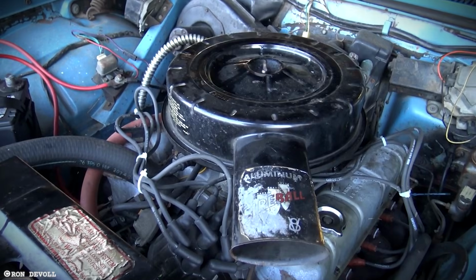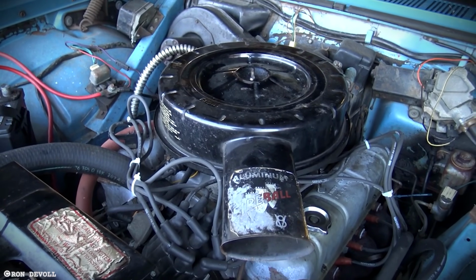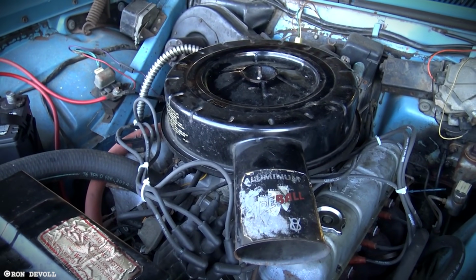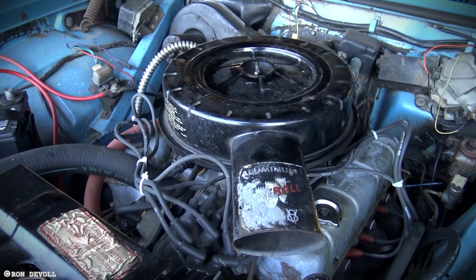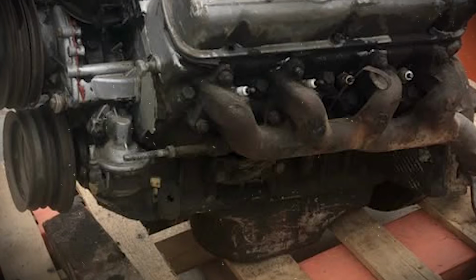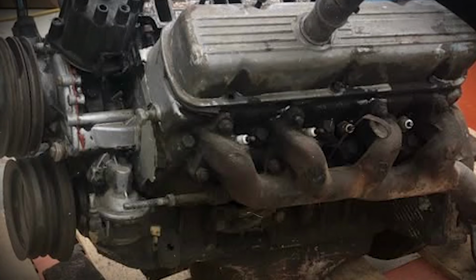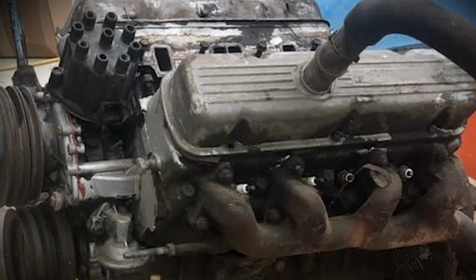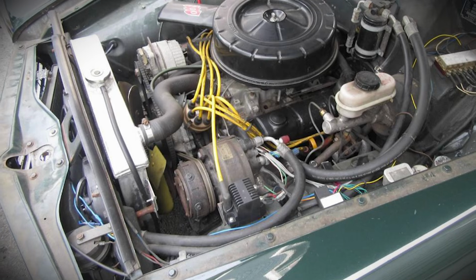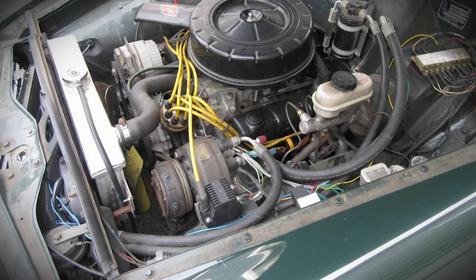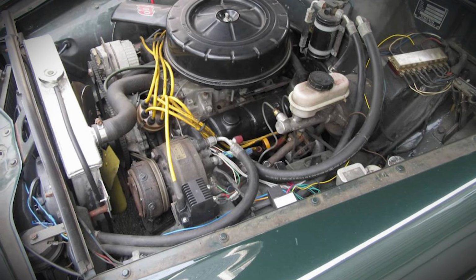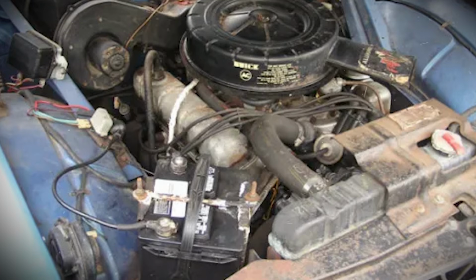Each gasket cost 3 times what a conventional one did, but it worked. The cylinder walls presented another challenge. Aluminum is too soft to handle piston rings directly. The team developed a process where iron cylinder liners were cast in place during the block molding process. The aluminum would shrink around the iron as it cooled, creating a mechanical bond stronger than any adhesive.